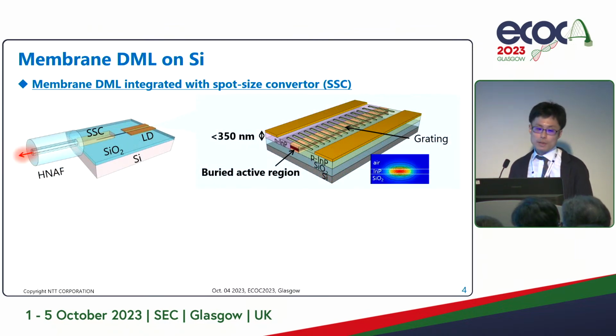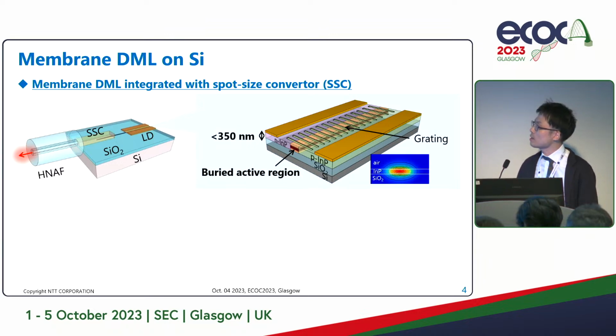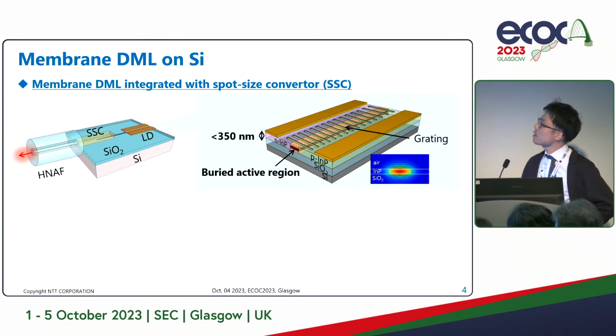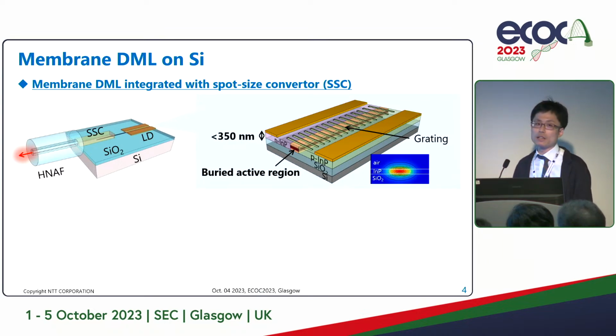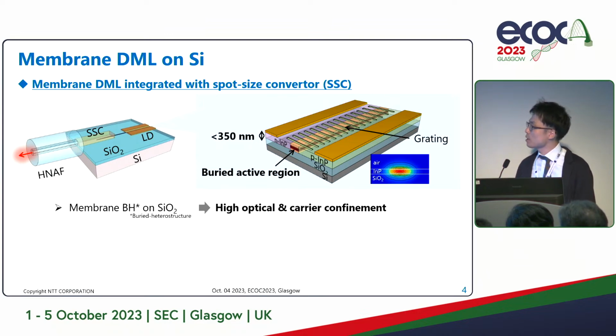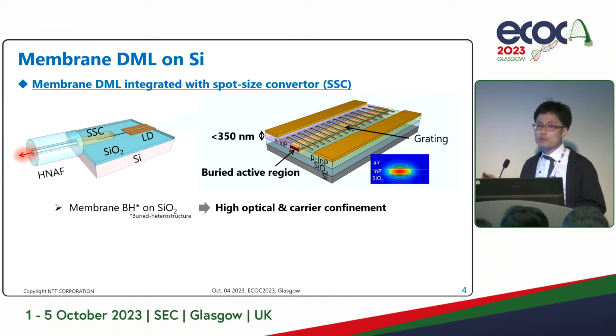To meet these requirements, we're developing a membrane DML on silicon. The device consists of a membrane structured laser together with a spot size converter, so that efficient optical coupling to the HNAF (high-NA fiber) is achieved. The device itself has a very thin, let's say 350 nanometer thick, III-V membrane layer buried with a PN-type indium phosphide layer and sandwiched between low refractive index silicon-based materials, so that we can achieve high optical and carrier confinement. They both help to reduce the power consumption.